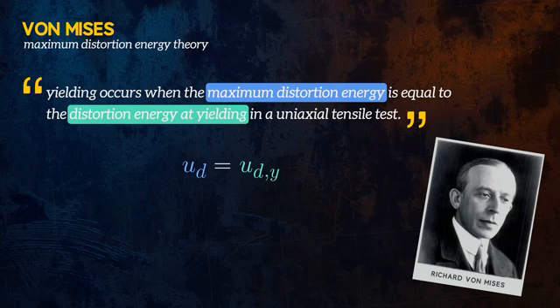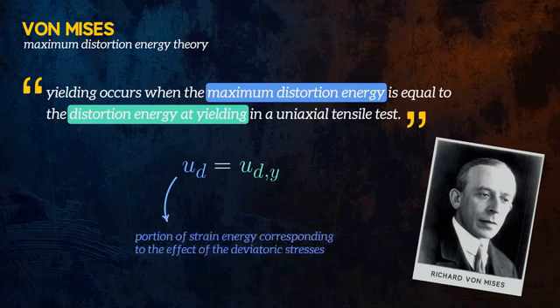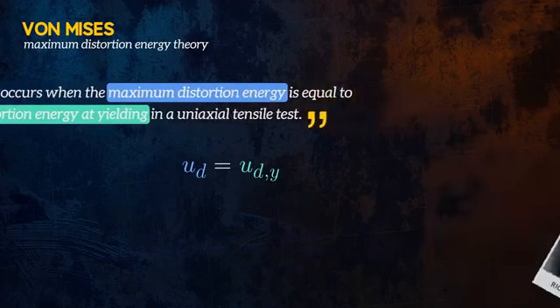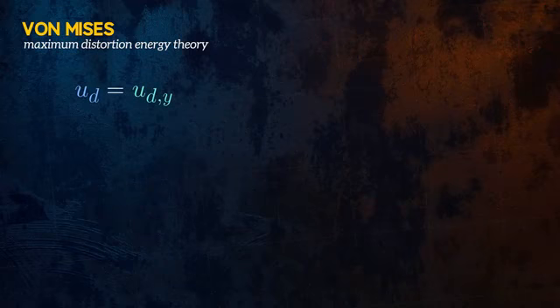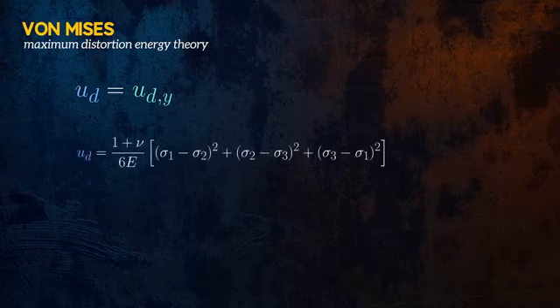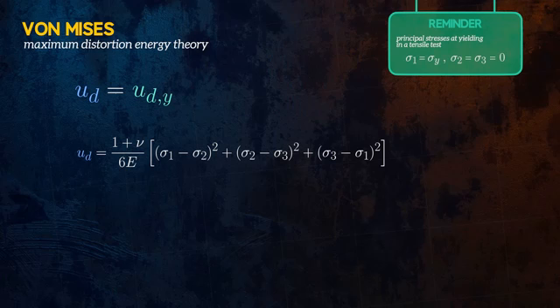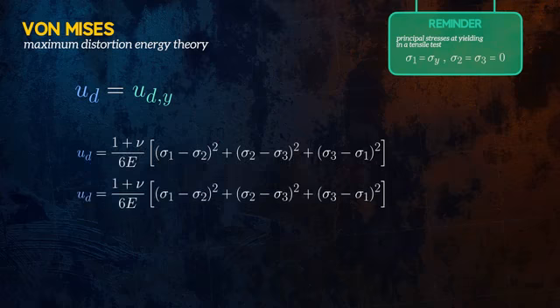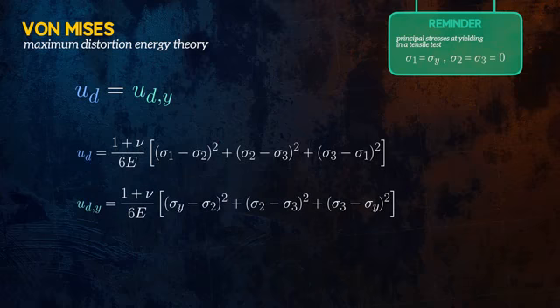So what is the distortion energy? It is essentially the portion of strain energy in a stressed element corresponding to the effect of the deviatoric stresses. The distortion energy per unit volume can be calculated from the principal stresses using this equation. We know that at yielding during a tensile test, the maximum principal stress is equal to the yield strength of the material, and the two other principal stresses are equal to 0. So we can calculate the distortion energy at yielding in a tensile test by plugging in the appropriate principal stress values.